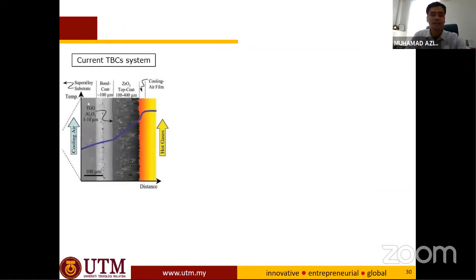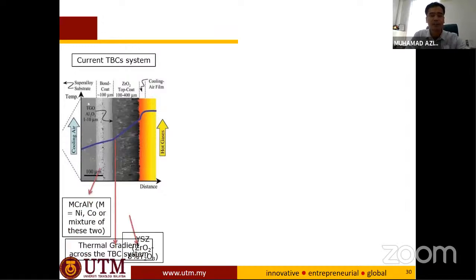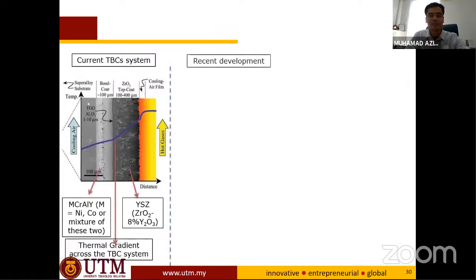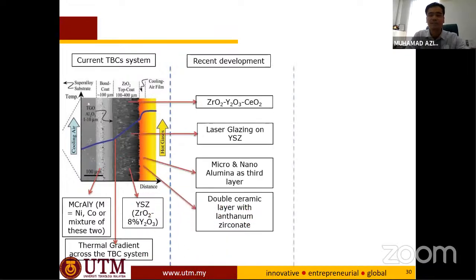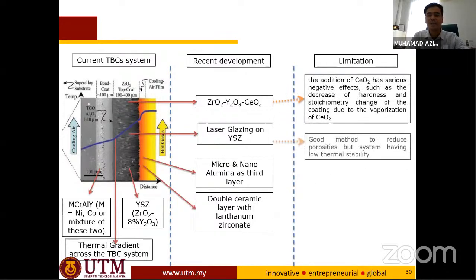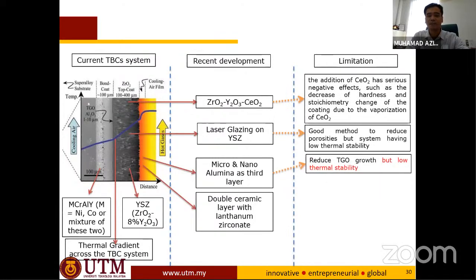So we have the current here. This is the one I showed earlier. This is quite an interesting slide. Recent development, we have all this. Each of these has its own limitation. For example, nano alumina is good. As I said, it can reduce the TGO growth. You can have a thin layer, but low thermal stability because this is alumina, isn't it? It cannot withstand high temperature. It's about the temperature of the YSZ.